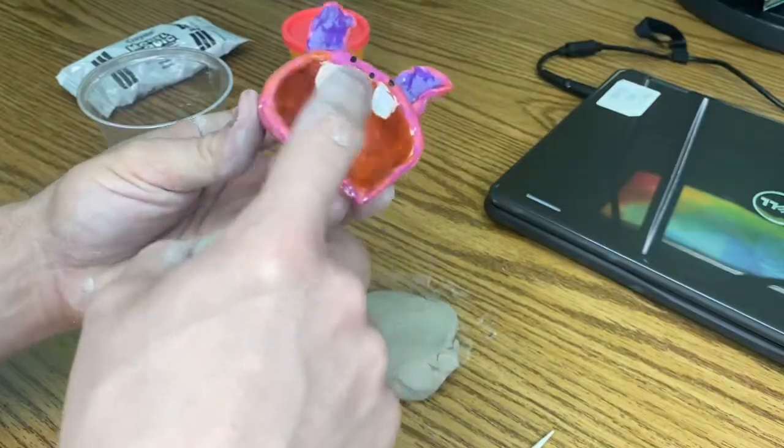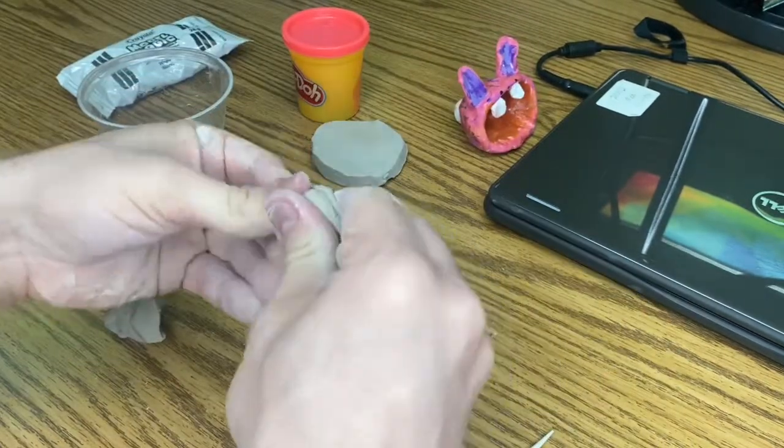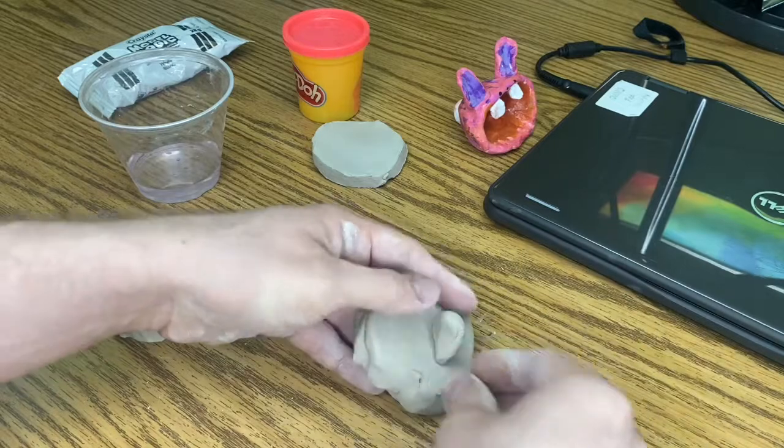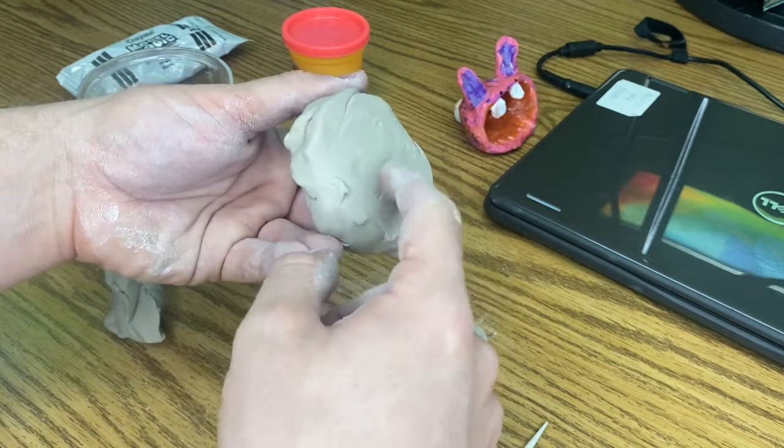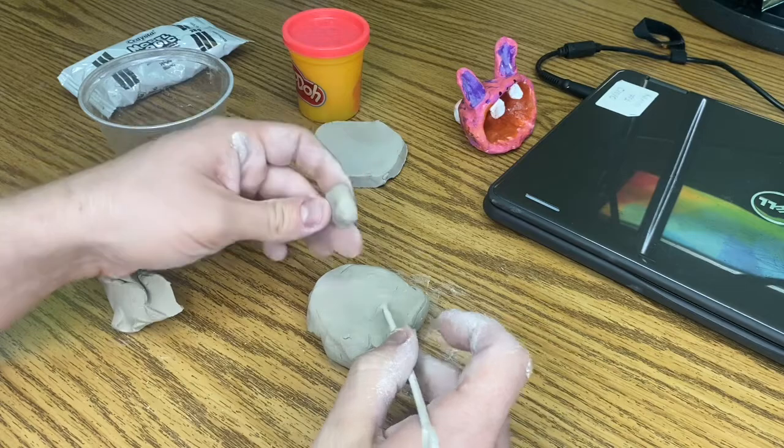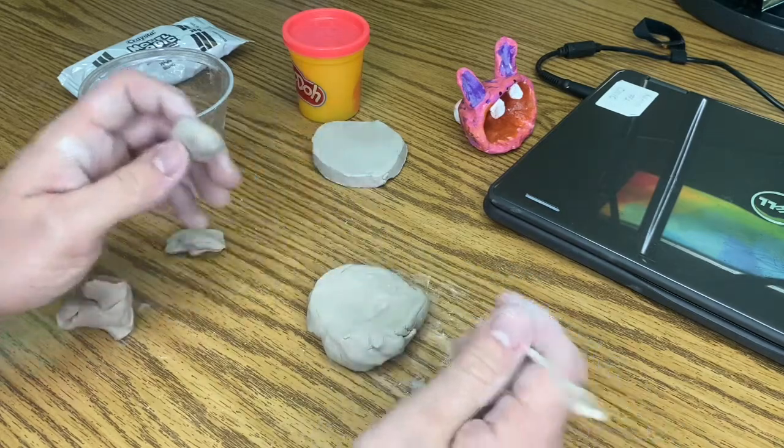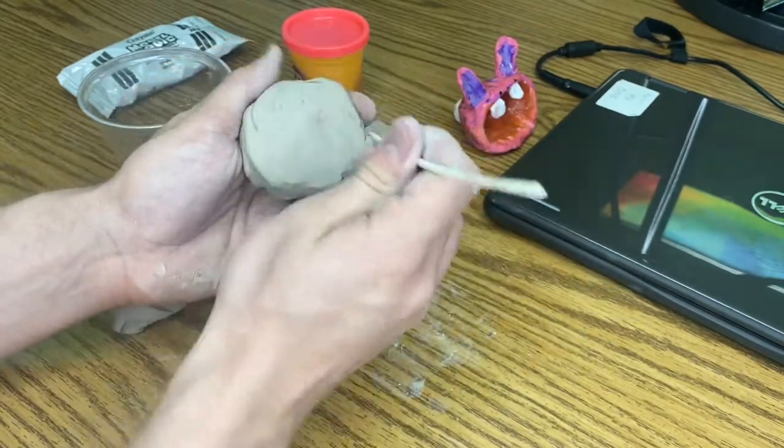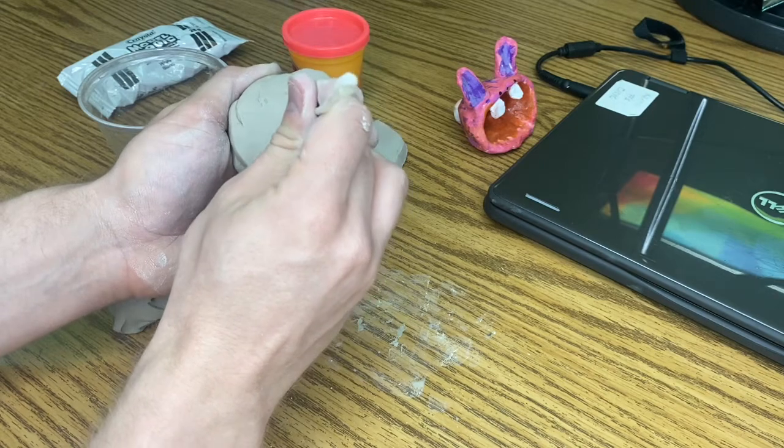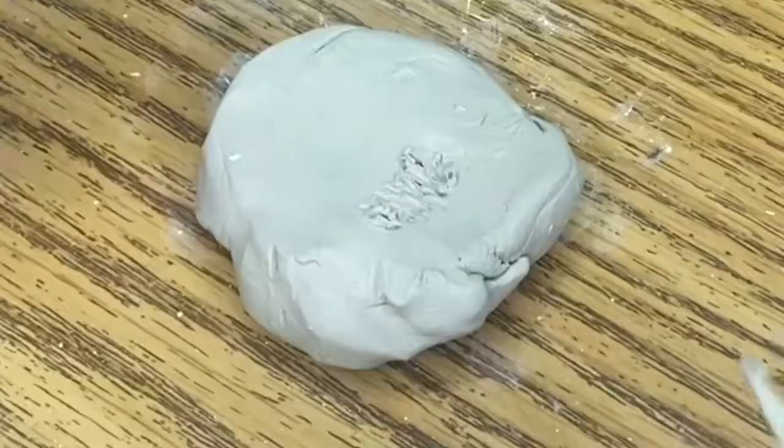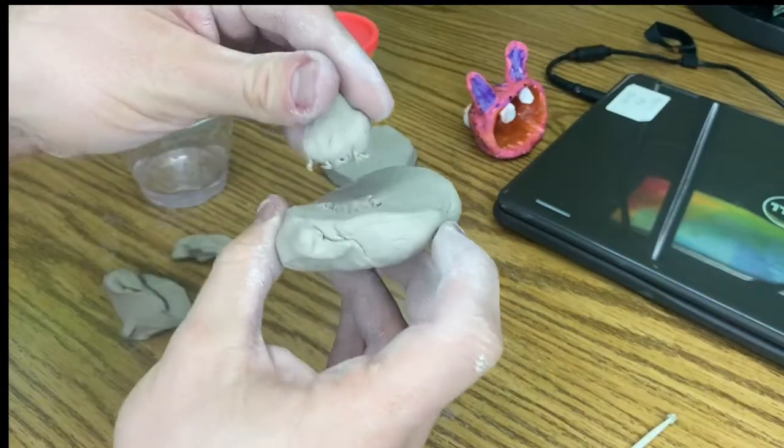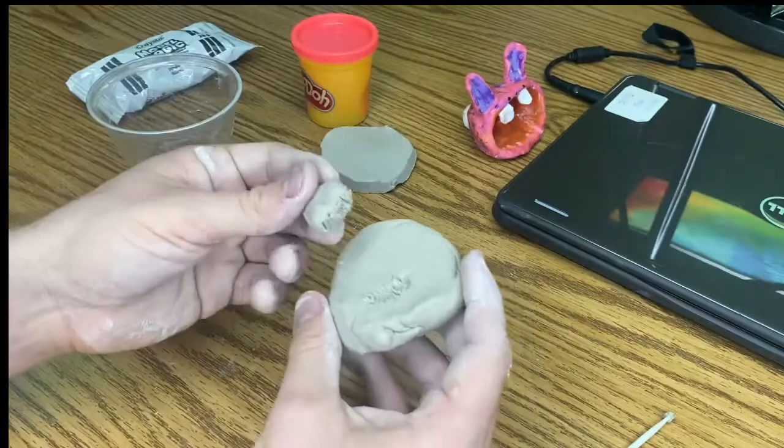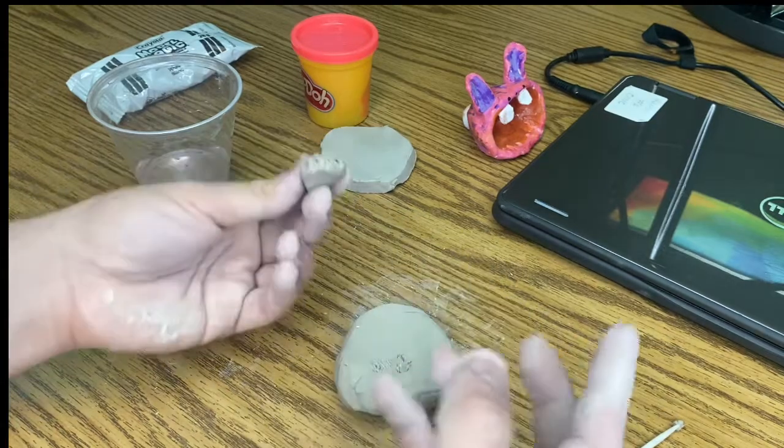They had to slip and score teeth and ears. They made something that they wanted to put on their clay. But with clay, you can't just stick it on there because when this fires, when it goes in the kiln, guess what? It's just going to pop right off because there's going to be an air bubble in there and it's going to explode. If I want to attach something onto this piece and I don't want it to fall or break off, you're going to have to score it. Score it means you're taking something like this plastic needle here and I'm just drawing little marks, little tallies in different directions. I'm also going to draw marks and tallies on the thing that I want to attach. This will connect the two pieces a little bit better and there's less chance of an air bubble. But now we need to add slip. Slip just means clay and water. It means adding water to the clay.